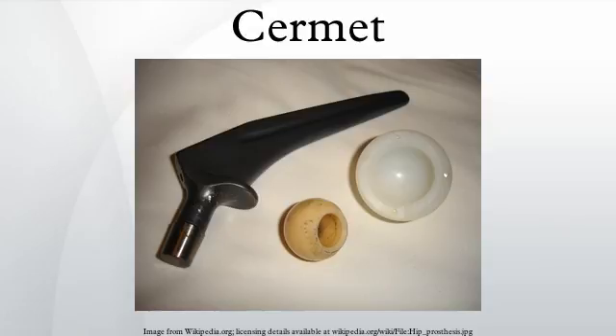Quality control in manufacturing these ceramic metal composites was hard to standardize. Production had to be kept to small batches and within these batches, the properties varied greatly. Failure of the material was usually a result of undetected flaws usually nucleated during processing. The existing technology in the 1950s reached a limit for jet engines where little more could be improved. Subsequently, engine manufacturers were reluctant to develop ceramic metal engines.